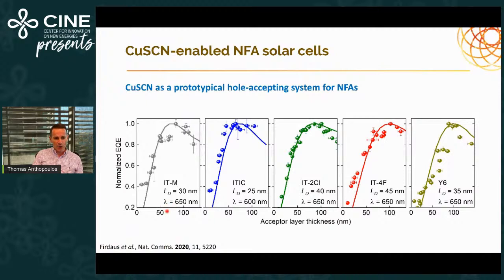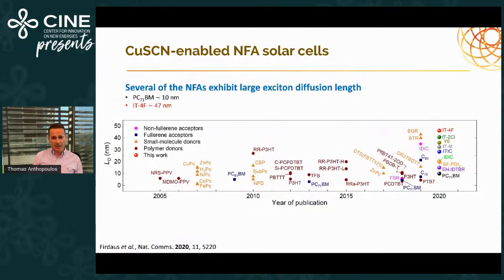And with the aid of modeling, we're able to extract the exciton diffusion length in these systems. And the summary of those external diffusion lengths appears here. This is actually most of our results extracted from this study. And as you can see, from PCBM, we extracted a number around 10 nanometers.